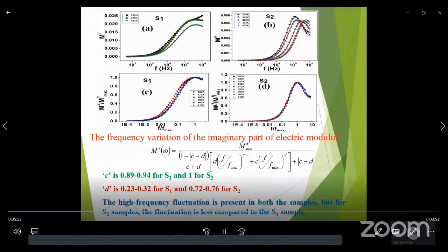The Bode plot of the impedance spectroscopy at different temperatures of S1 and S2 sample has been shown here. A prominent relaxation peak has been observed which shifts to the higher frequency side with an increase in temperature, and this reflects the relaxation time decreases with an increase in temperature. The frequency variation of electric modulus has been discussed here.